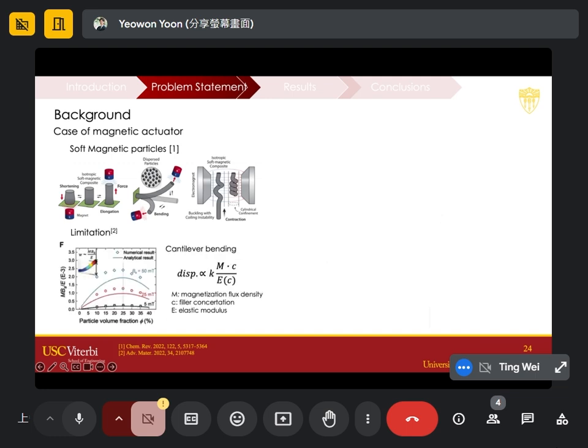So very easily to explain, if you have a cantilever beam full of iron particles, and then you try to bend it with the magnet, your deflection can be determined by a few factors. If you just increase the material concentration, that will make the whole cantilever beam pretty stiff, therefore minimizing deflection. But if you reduce the concentration, you also reduce the actuation motion. So there's a little bit of a trade-off. If you just increase the particle volume fraction, that will basically reduce the bending.